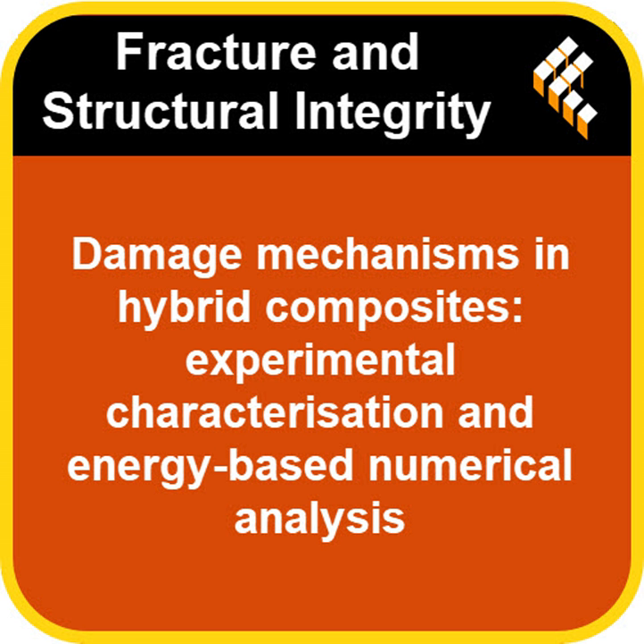But there was a bit of a surprise there, right? This study mentioned that where the fiberglass layers were positioned had an interesting effect. Yes, that was a key takeaway. Really interesting. They found that when they put more fiberglass layers on the compression side, the side being squished during bending, the composite could actually handle slightly more force and bend a little bit more before failing.